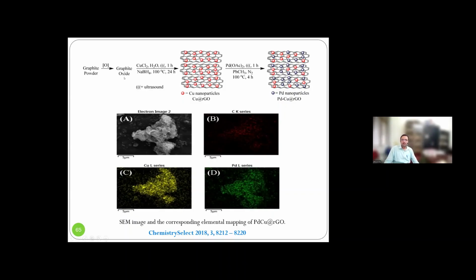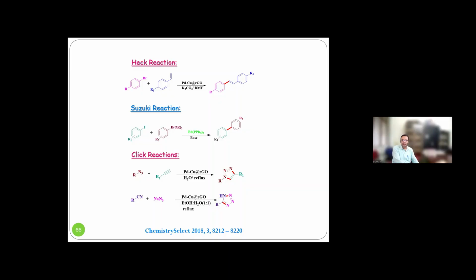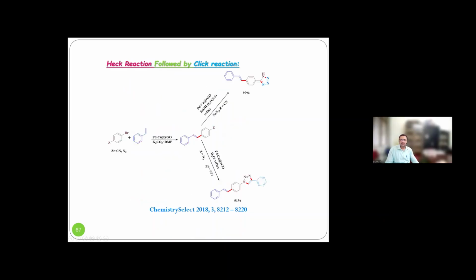So we doped first copper on the surface of GO and then palladium on the surface of the GO. This is elemental analysis. This yellow color is for copper and palladium is green color. So this confirms that both elements are doped on the GO surface. Then we applied this palladium copper GO at the Heck reaction, then Suzuki reaction, then also triazole synthesis, 1,3 dipolar cycloaddition reaction, then tetrazole synthesis. Every reaction went successfully. Then we did first Heck reaction, then tetrazole synthesis, and first Heck reaction, then triazole synthesis.